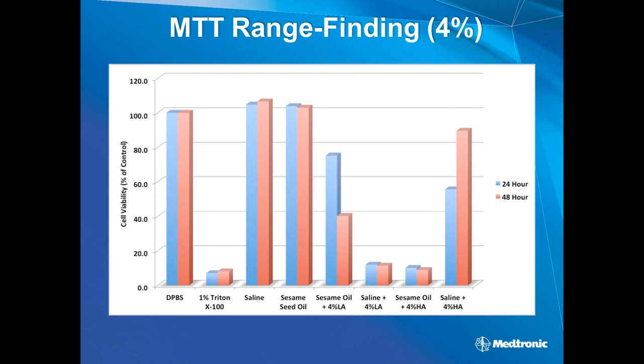So here's a bar graph that shows cell viability. We did two endpoints, 24 hours and 48 hours. And I'll go left to right on here. This is phosphate buffered saline. This is cell viability. So thankfully our saline is not killing any cells after 1 or 2 days. Triton X-100 was our positive control. If you've ever worked in a chemistry lab, you're familiar with this one, because it's used as a detergent. It's a good skin irritant, not as powerful as sodium lauryl sulfate, but adequate for our purposes.